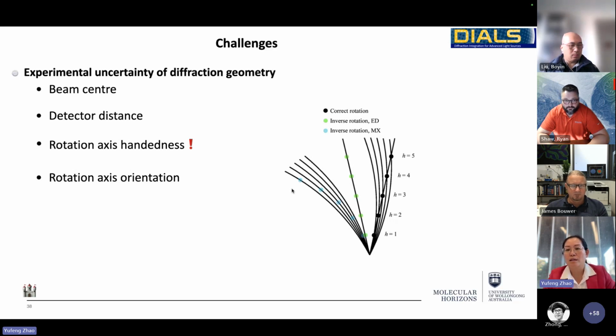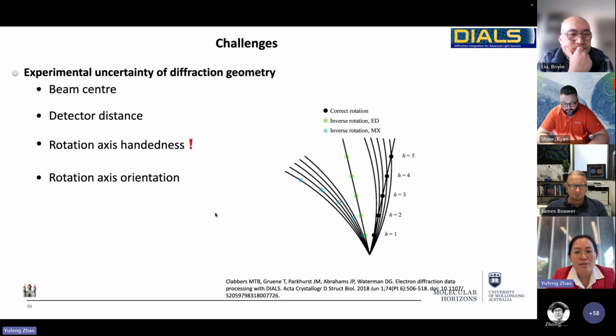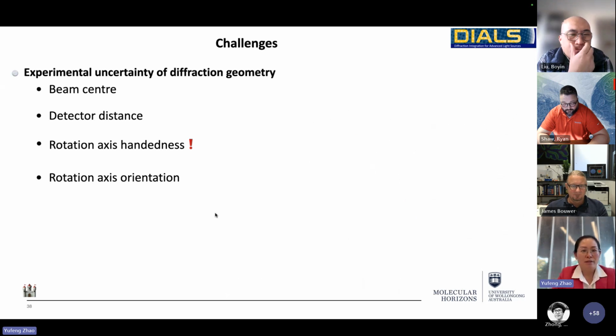so you wouldn't make such a mistake. But for electron diffraction, as we mentioned, because the Ewald sphere is almost flat, even if you use an inverted rotation axis to process, the dots still line up nicely. They just rotate away by a little amount and still line up nicely. We can still process the data and get a structure in the end. But guess what? The structure we get will be inverted, so the wrong hand. This is something to be really careful about.